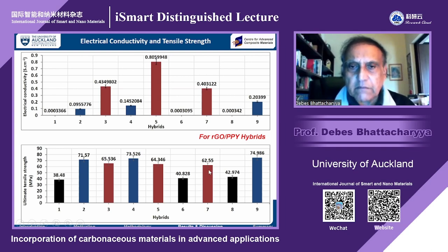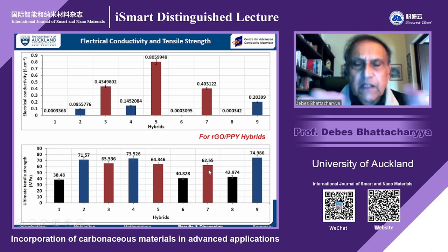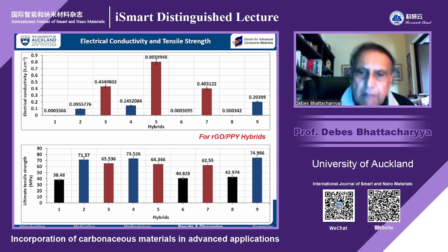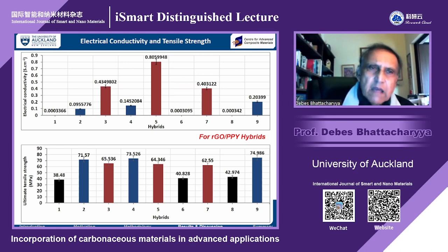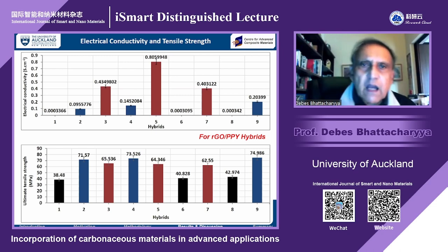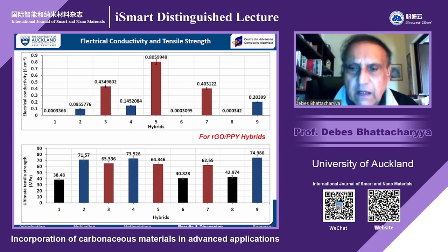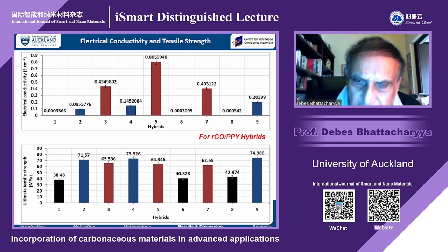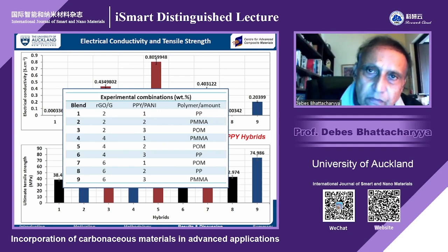You can go for this as well. So it's up to you. But the results were not bad, but we were not happy because it was still about 0.8. We wanted to get much higher conductivity. So what we did was, and these are the combinations, you see 5, 5, 3, 7, you can see how we combine. This was done with melt blending process.